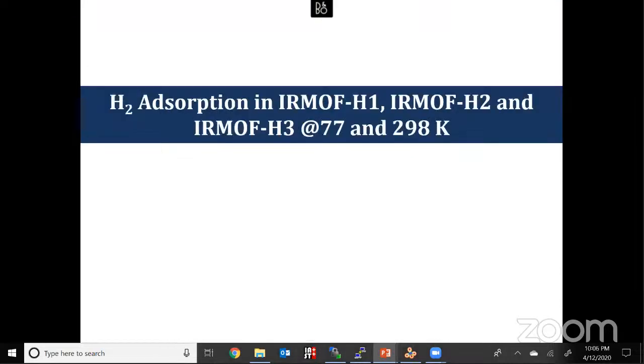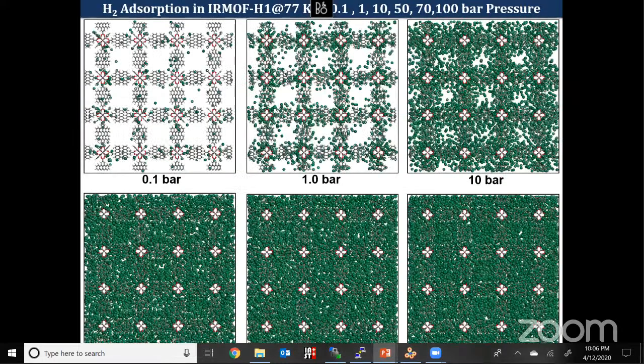For the framework atoms also, we need to have a partial atomic charge in order to mimic the experimental condition. We actually need a real system, so we need to give all these parameters carefully and correctly in the input file. So these are the simulation snapshots of adsorption at various pressure ranges. Here you can see the advantage of using this linker. If we have a single benzene molecule in the connector part, we are able to store two hydrogen molecules at very low pressure, and a maximum of more molecules at higher pressure. But if you have more attraction sites in a linker, that will help improve the material's gas uptake property at moderate as well as higher pressure.